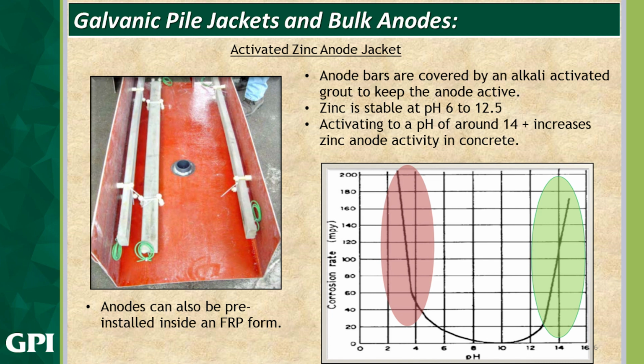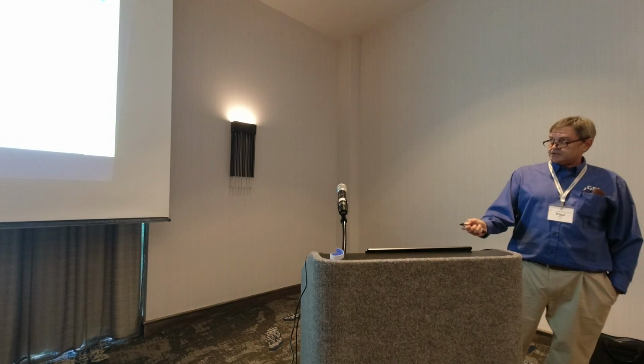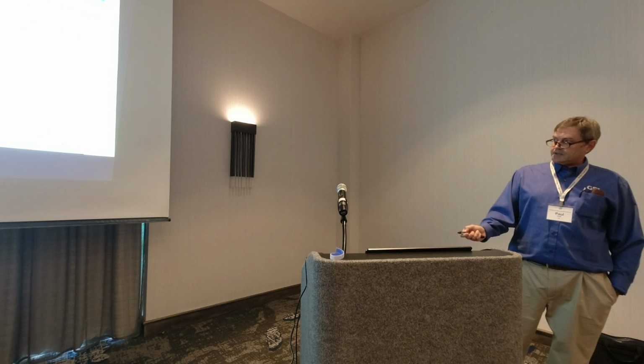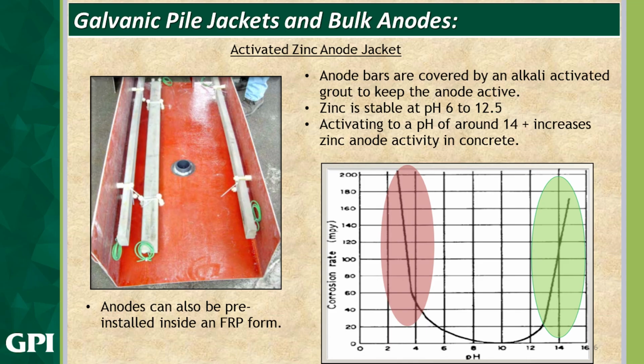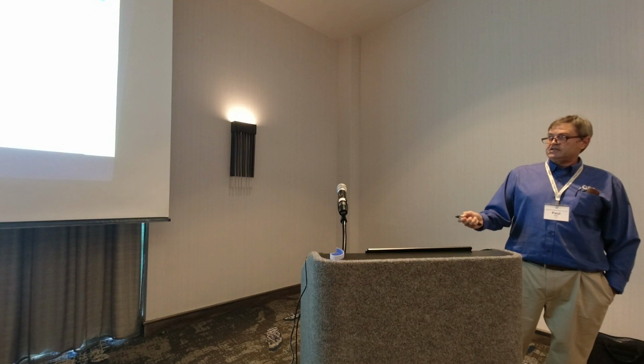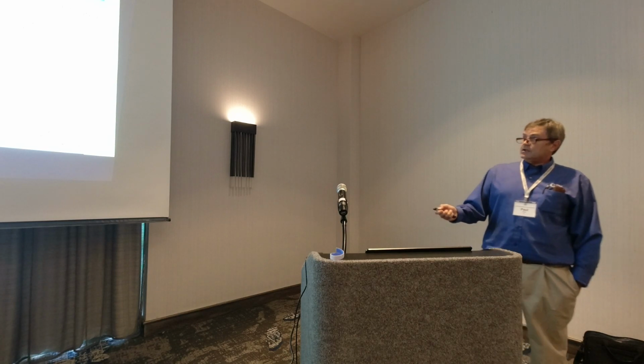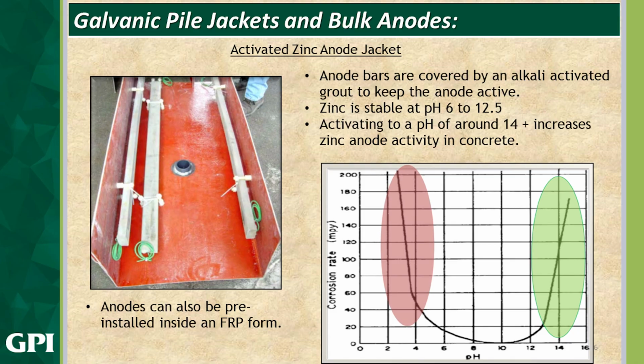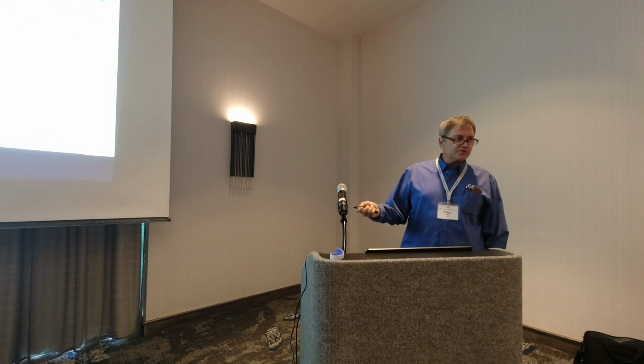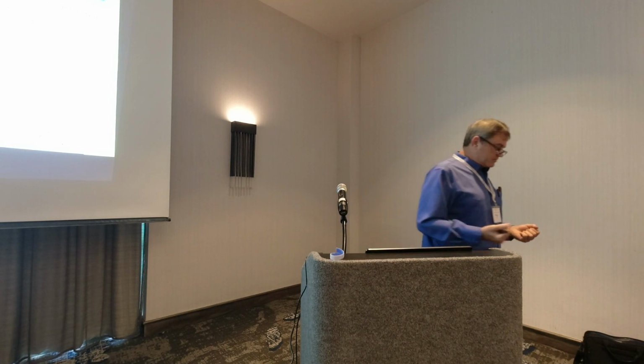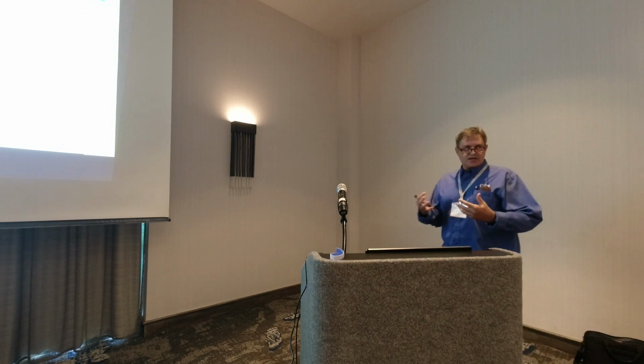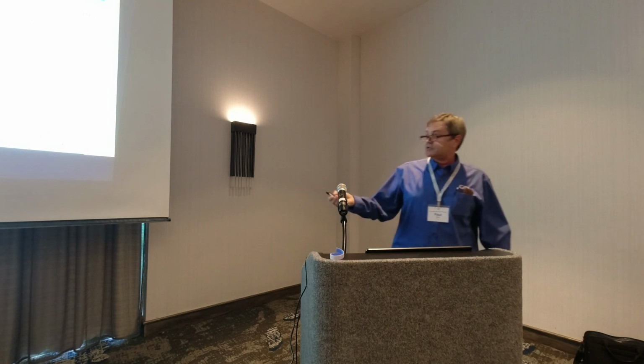This chart is showing the stability of zinc. So you can see the curve here. What we're trying to convey is that above pHs of 12, zinc becomes very active and corrodes. Below pHs of about 6, it also becomes active and corrodes. So in this area, we're pretty good, and no corrosion takes place. But in these areas, that's where our zinc becomes active. So activating to a pH of about 14 increases the zinc activity, and they utilize encapsulation materials around the anodes to keep the zincs active. And they can create their own corrosion products and deactivate themselves. These encapsulation products help keep that from happening.